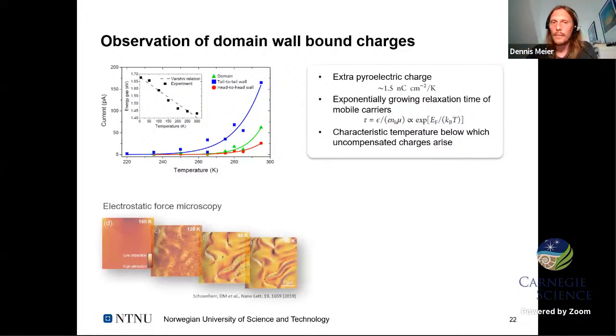And you can really see that when we do electrostatic force microscopy measurements. We don't see any electrostatic forces at temperatures of 160 Kelvin. When we cool the system further and further down, you see that these lines are showing up, and at 80 Kelvin, 40 Kelvin, they form exactly this pattern, which we already know from the PFM measurements and the domain walls with the 6-fold meeting points. So suddenly, when I make the system cold enough, I see the strong electrostatic forces from the walls, showing that we no longer have fully screened walls.